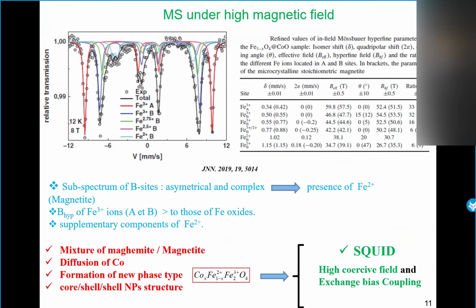The spectrum for the site A subspectrum is classical, characterized by a narrow line. We can reproduce this subspectrum easily using one subspectrum. But the subspectrum of site B is more complex, with complex hyperfine structures. The shape is typical of magnetite because of the presence of iron 2+, but using the 5 models of magnetite, it's not possible to reproduce this subspectrum correctly. So we need to add a new subspectrum of iron 2+. The hyperfine parameters for this subspectrum are different from those of the iron 2+ of magnetite. So the description shows the presence of a supplementary component of iron 2+ in the structure.